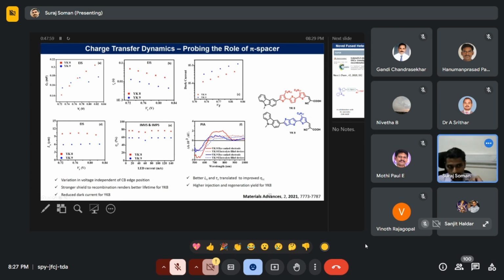to the semiconductor. And what we have also observed is that we did some very interesting photo-induced absorption measurements, PIA measurements, with and without the electrolyte system. The solid line represents the absorption of your oxidized species. That means you make the device without any electrolyte, you shine the light onto the device, then you probe the system, and automatically your dye will get excited, and you map the absorption of your excited species. So that is what you see here.